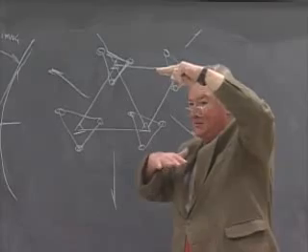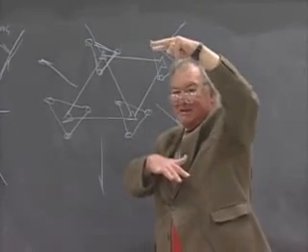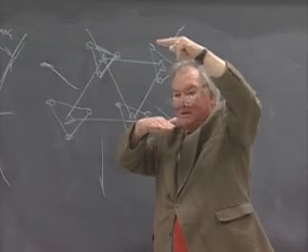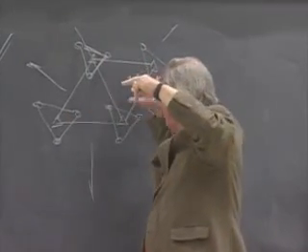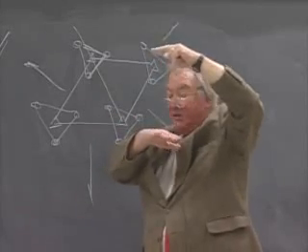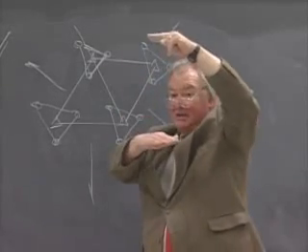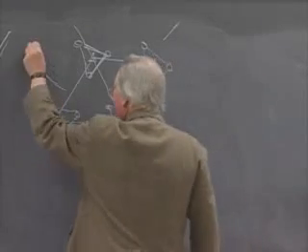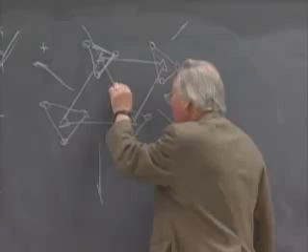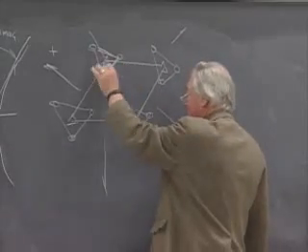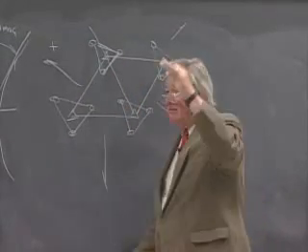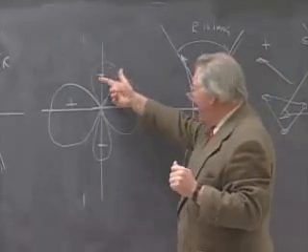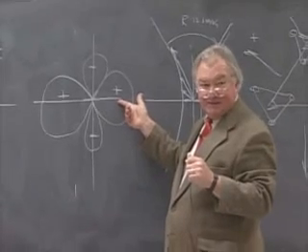But the spirals are in part held in this extended form by repulsive interactions on like chains. So when these spirals move apart as a result of large thermal expansion in the plane normal to the chains, they relax a little bit. So you have a large positive thermal expansion here, but in one direction along the normal to the hexagonal net in the structure, the thermal expansion is negative. And that gives you a variation of property with direction that looks exactly like this.